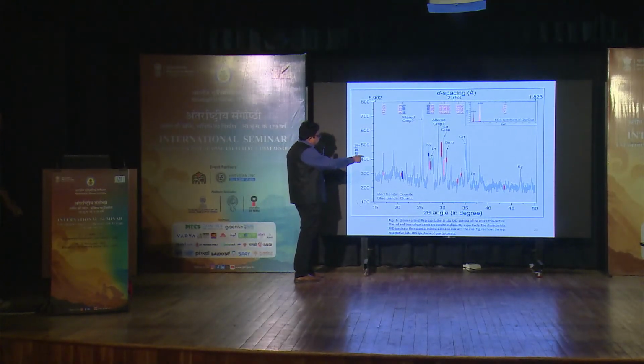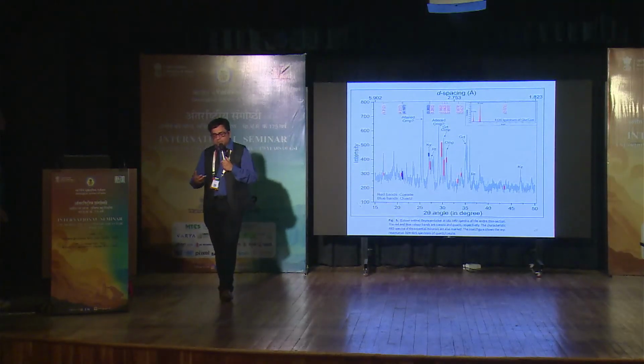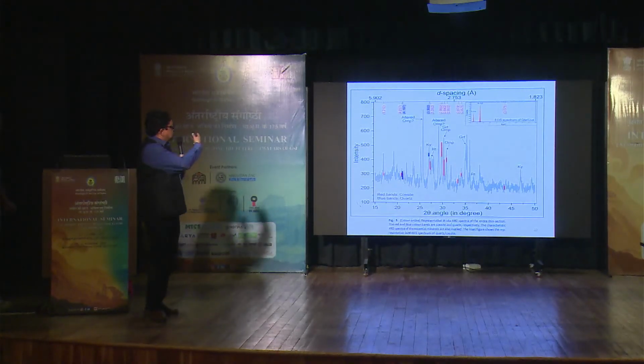and you can get the spectra, which confirm that all the red bands you can see here are coesite. Of course, blue bands are quartz. So in our eclogite, we do have coesite, and we do have quartz, because quartz is always associated with coesite, because coesite is a high pressure polymorph. As it is brought up, it is metastable and inverts to quartz, but it's not necessary that the entire coesite should invert to quartz. That's why we are finding a few coesites intact and a few quartz grains. That's what polycrystalline quartz means.